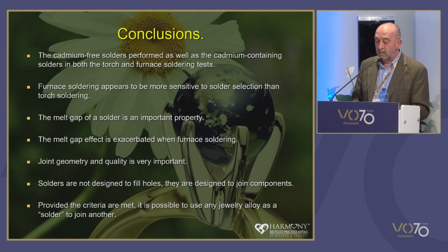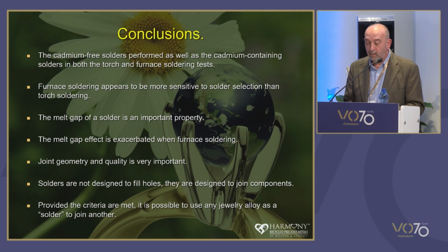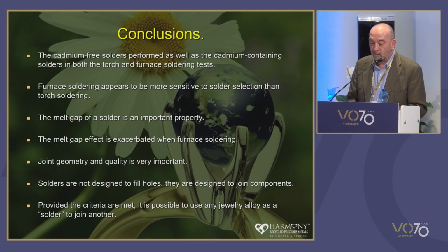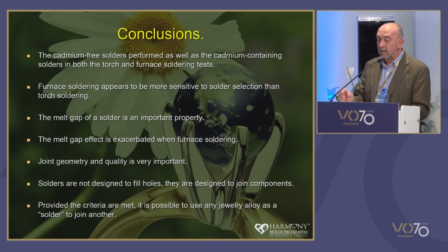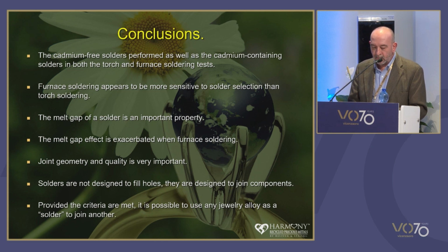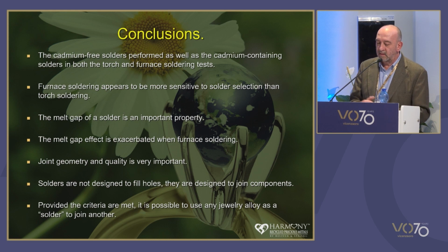The melt gap of the solder is an important property. A broad melt gap can decrease performance, and this is important because this is some of the information that's available to the purchaser. And the melt gap effect appears to be exacerbated when you furnace solder. Low melting point volatiles can be lost, and the change in melting temperature of the residual solder can potentially be raised above that which you set on your furnace.